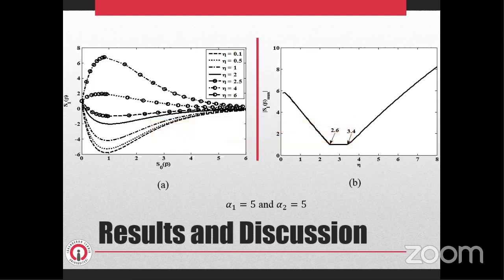These results imply the existence of lower limit eta 1 and upper limit eta 2 of eta. When alpha 2 is greater than 0, regardless of the value of alpha 1. Figure B indicates the variation of the absolute value of the maximum amplitude of the perturbation for the same system parameters. For this case, eta 1 and eta 2 are determined as 2.6 and 3.4 respectively.